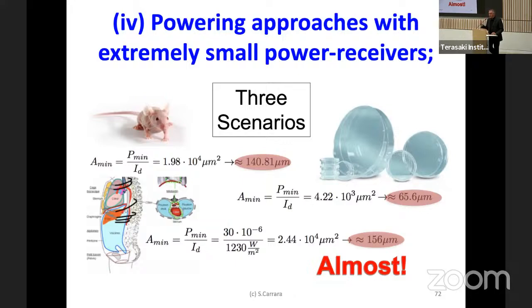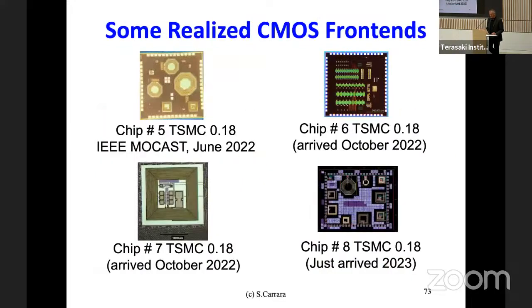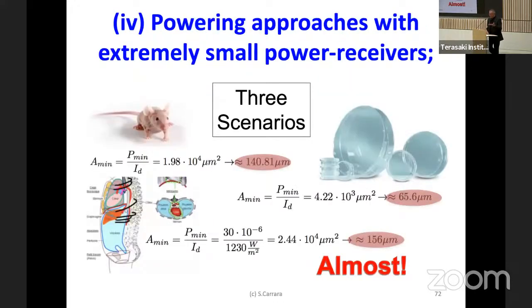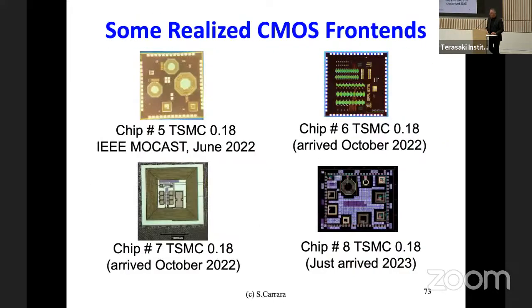With the digital potentiostat by Paolo, we are at 9 nanowatts. So we can really again go down two orders of magnitude, or three, with respect to this coil size. Because this was driving us around 150, we started from under 50. This is one of the latest babies we have received. You see here the coil is realized not anymore with a metallic thin film, but by exploiting the metal layer inside the CMOS. So it's received directly from the foundry, and inside the area of the coil, we have all the electronics we need.